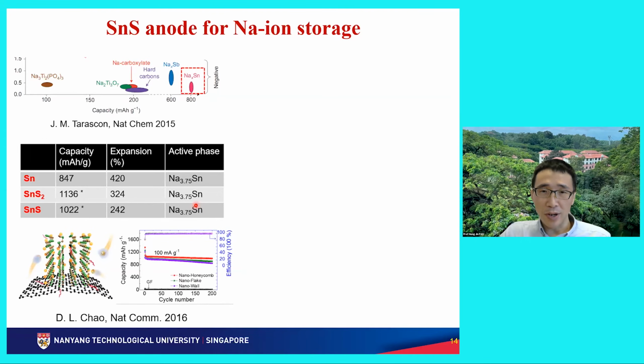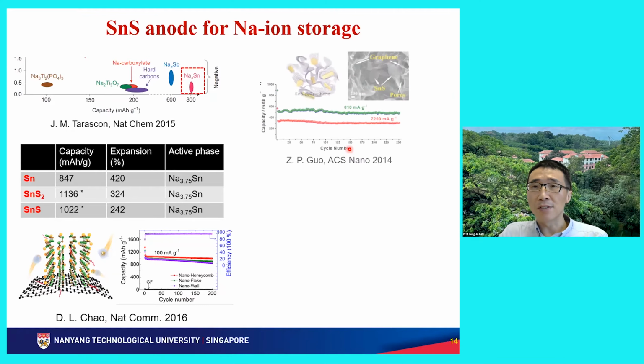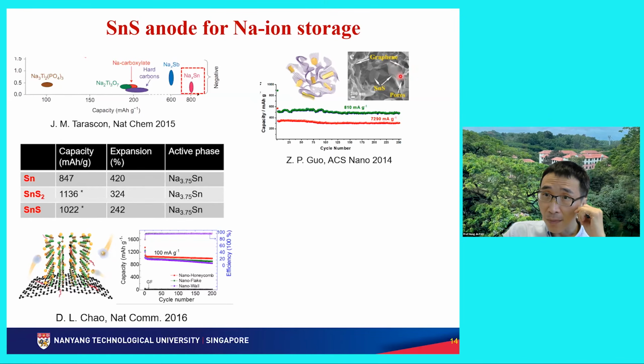So people use all different kinds of methods and strategies to improve the rate performance and the stabilities of these tin-based materials. If you look at the first article, Nature Communications 2016 from NTU, they got a very stable high rate, that means very fast charging and discharging capabilities, of this tin monosulfide anode. The other work is from the University of Wollongong, from my friend Guo Zaiping. They grow these tin monosulfide particles, you can see these granular particles, within the graphene, which is this three-dimensional graphene structure. And they find that, okay, this graphene can provide very fast electron conduction paths, like in this schematic diagram, and also can stabilize the whole tin monosulfide so that the capacity is higher and stable.